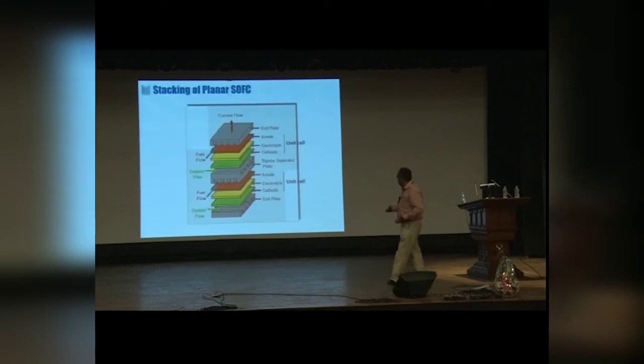So here, as you can see, for example, for 24 micron, you have this area specific resistance, and the current density you will get is 1.55. If you multiply this with 0.7 volt, then you will get the power density, that is 1.09. So one cell can give you a power density of 1 watt per centimeter square in the normal case. But I will show you how one can increase it. But before that, let me tell you how to make the stack.